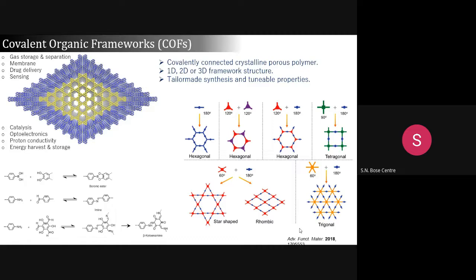So people started looking at more stable linkages like imine. The problem is that while you are constructing this one, there will be a lot of defects, which will not allow you to get a very crystalline form. So you should introduce some kind of chemistry which can rectify your defects. That is why this kind of dynamic covalent chemistry has been used, which can break and make during the process.